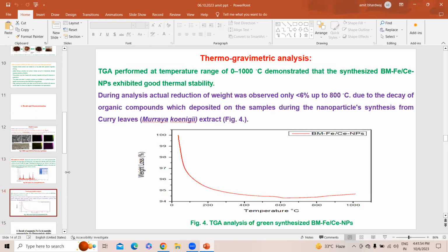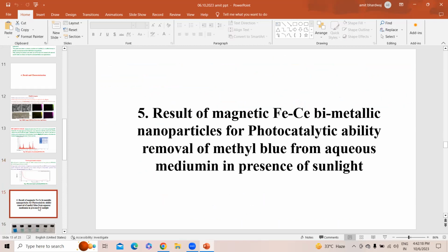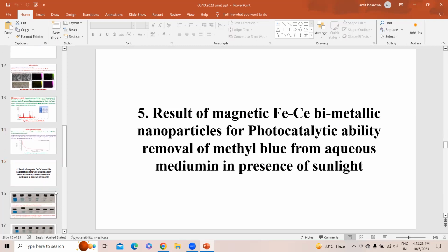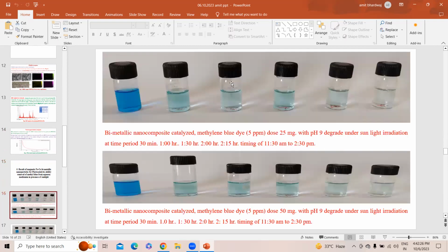Another characterization is TGA, which indicates the stability of the nanoparticles. About 6% of the material is lost in weight at 800 degrees centigrade, due to decay of the organic compounds, that is the decomposition of the sample during nanoparticle synthesis from curry leaves. After that, the nanoparticles are used for the degradation of dye in sunlight. Some experiments were done in the lab.